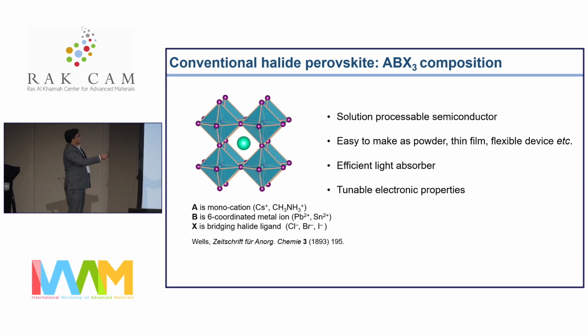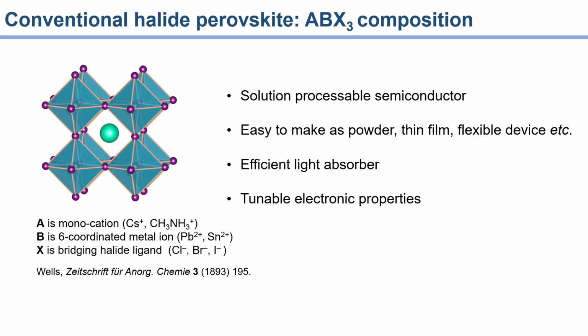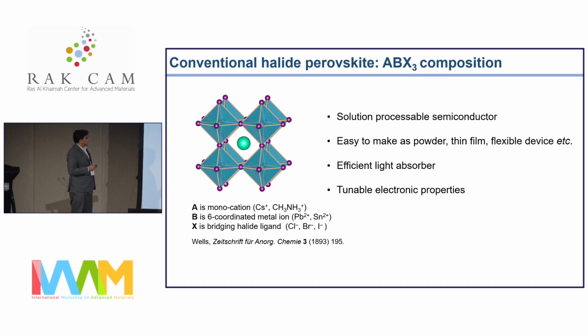A perovskite is basically an ABX3 type of composition with crystalline nature, where A is a fairly large cation, which is typically cesium in all-inorganic and methylammonium in hybrid perovskites. Then the metal we have is typically 2+, and in most systems it is lead 2+, and in some cases tin 2+, and then halides we can choose at will. When this metal and halide combine together, they form octahedral coordination, and the corners of these octahedra connect in all the directions, all 3 axes, to form a 3D lattice, which is negatively charged, and also has a large cavity called the A-site cavity. Now this cation can easily go and sit in the cavity and form a stable lattice.